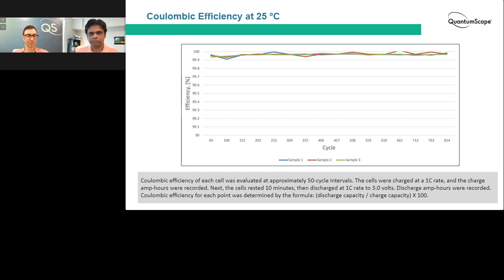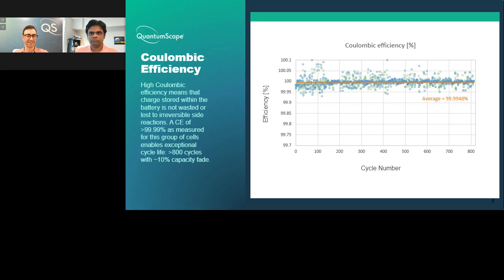And so this chart was shown in the third-party report, showing the coulombic efficiency every 50 cycles. But we actually want to concentrate on this next slide, which goes a little bit into even further detail that wasn't shown in the chart in the report. So this is the coulombic efficiency of all three cells on every cycle during the test. And if you just average all the data points here, the average coulombic efficiency is roughly 99.995 percent, which sounds like a pretty high number, pretty close to 100%. Maybe Venkat can explain why this is important and what the requirement for coulombic efficiency is.